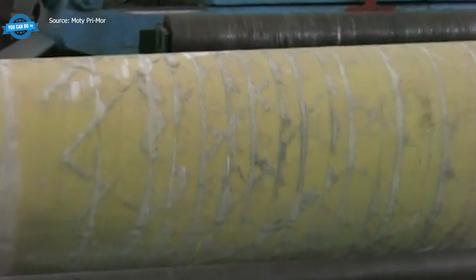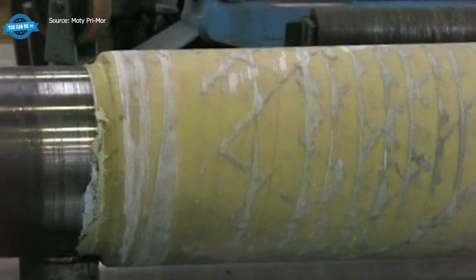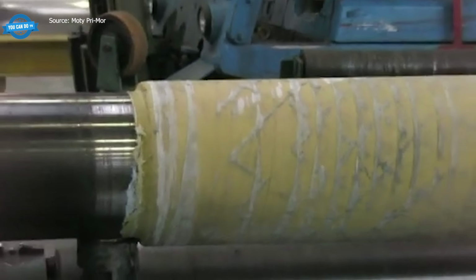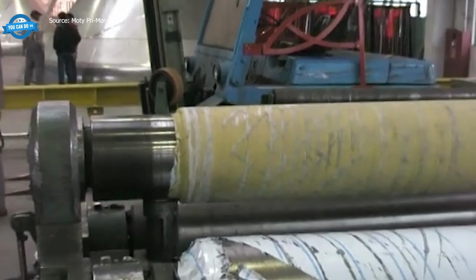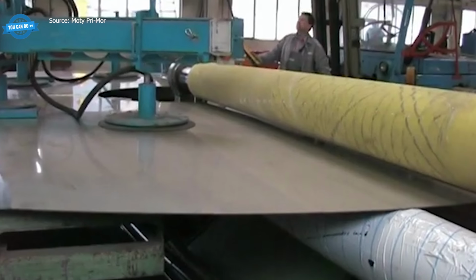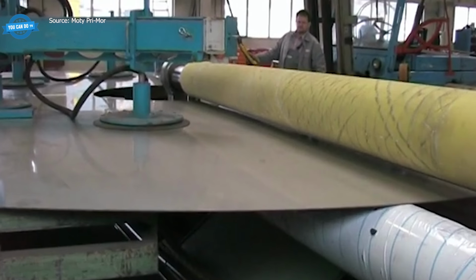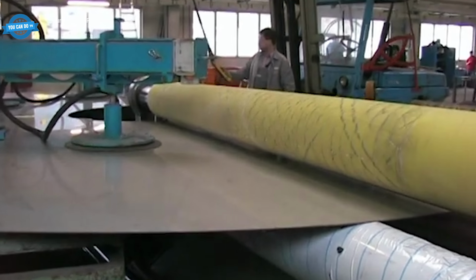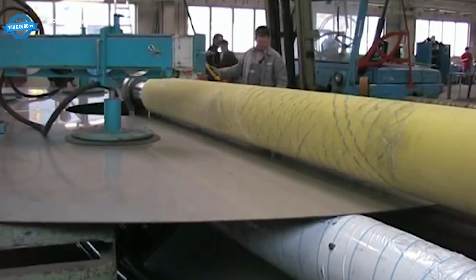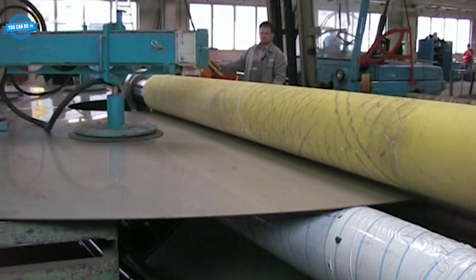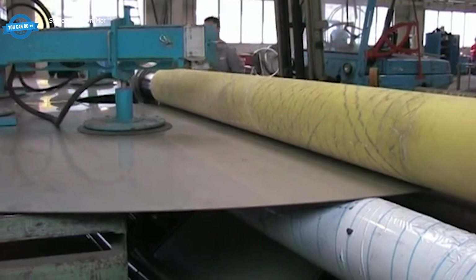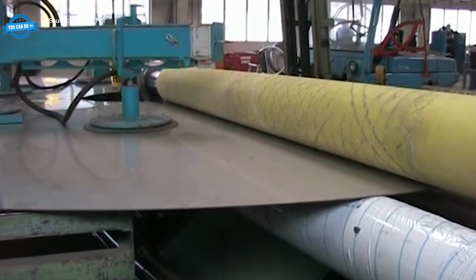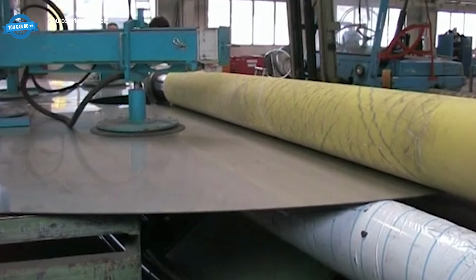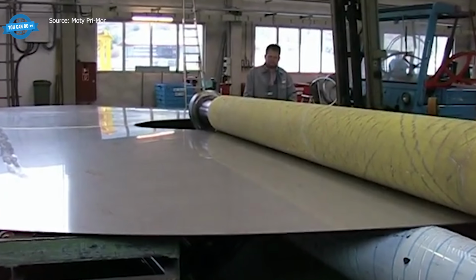Forming a cone at large diameter is one of the most delicate operations in the whole pipeline. A cone-stopping attachment slows the plate on the minor diameter side, forcing the steel to fan around the rolls. The side rolls are tilted at an angle matching the cone slope rather than raised in parallel. Forming happens across multiple passes, with the operator constantly checking that the two edges will close cleanly when the cone meets itself.